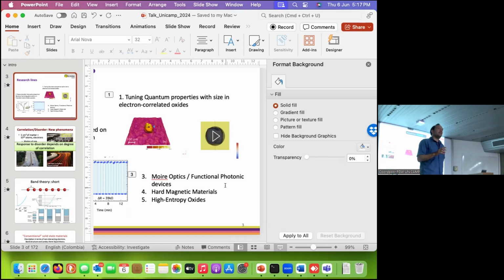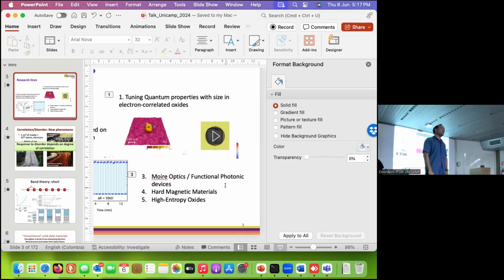And the idea was, and I haven't seen anybody trying this, that now you can change your beam by 180 degrees. So you flip the sample. And then by subtracting these two intensities, somehow you get information about the polarization. If you work out the math, you will see that you can get rid of a bunch of terms, and then you get just the term that depends on the polarization. What I wanted to see is the map of the atomic polarization distribution inside the particle. We did see something. We actually saw domains inside the particle, but we couldn't understand why. We haven't published that, so that is unpublished. If you want to talk about that more, I can.